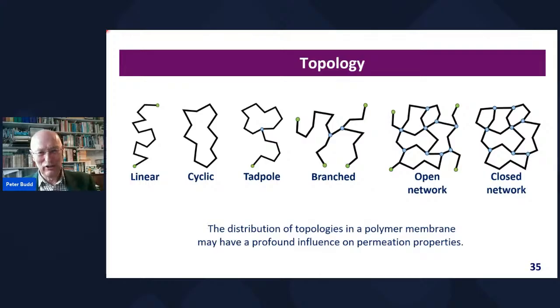Because we might draw a structure as though it's a linear polymer, an idealized structure, whereas the reality of what comes out of your polymerization may be a rather more complex mixture of different topologies. We may have cyclic, we generally have quite a lot of cyclic, particularly in low molecular weight. We have tadpole structures, branch structures, network structures. And the distribution of topologies for what is nominally the same chemical structure may have a profound influence on permeation properties.